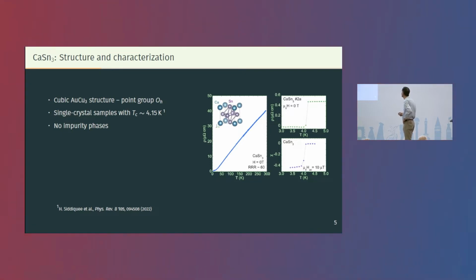And then it shows almost linear resistance. When you go at very low temperatures, you see the superconducting transition. What is nice is it is very narrow. Narrow means this is a good quality single crystal. What is important also, this number here. It seems trivial, but this is above the Tc of tin. Pure tin is 3.7. So this is not dirty tin, just to tell you, okay? And this is also seen in the magnetometry results.